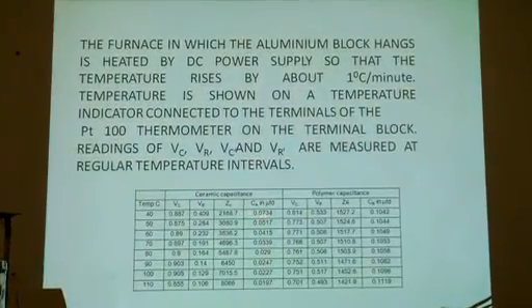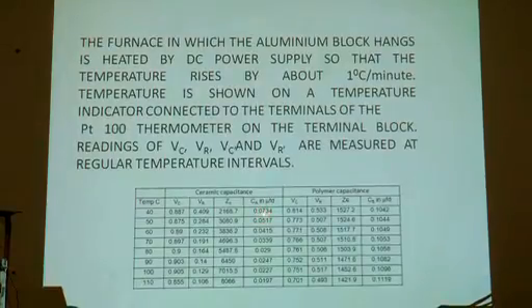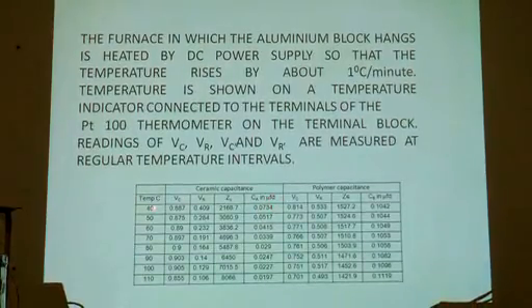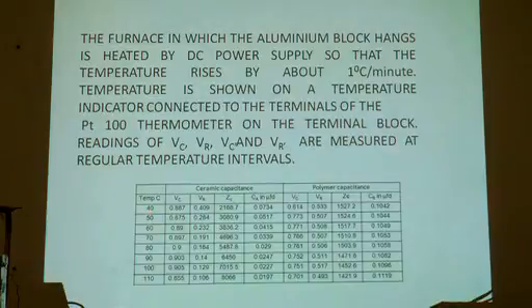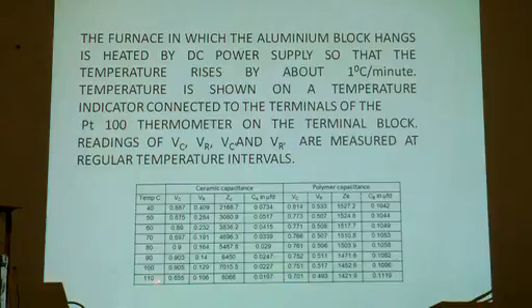You see that the capacitance has a value 0.073 microfarad at 40 degrees centigrade. It comes down to 0.0197 at 110 degrees. So, the ceramic capacitance decreases as the temperature goes up. These are the readings for the polymer capacitor. You see that the capacitance is nearly constant at 0.1 microfarad. It increases slightly as you go to 110 degrees.